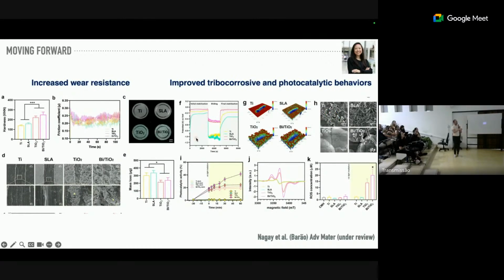And then you have also some data about hardness, some data about friction coefficient, some data about tribocorrosion. As you can see here, this is the drop of the potential when we are rubbing. As you may see, in the controls, SLA and machined surface, the drop was higher when you compare to the TiO2 surface, which means that in terms of tribocorrosion, the TiO2 surfaces were better. We also have some white light interferometer microscope image. We also have the material loss after rubbing. The material loss was lower for the bismuth and for TiO2.